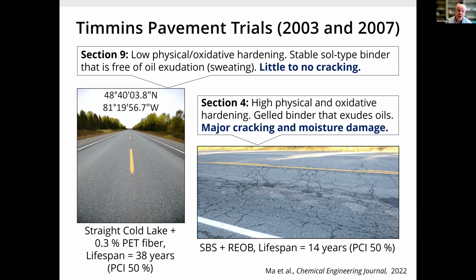Many municipalities can go to 30, 20, and some even go to 10 because they don't have the money to rehab at 50%. So you get 60, 70 years out of your roads, and that's the historical number for how roads would be built prior to Superpave. In the 60s, 70s, and 80s, we had one refinery in Oakville. They used super duper quality crude from Bow River. Petro-Canada, Bow River crude, very good asphalt, no waxes, and RAP wasn't an issue. Not too much recycling going on.